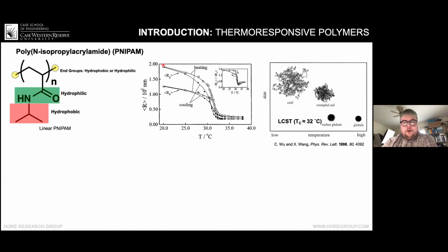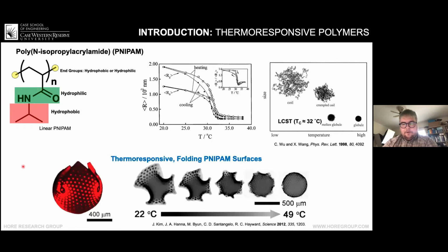So what's observed is that as you heat poly-NIPAM up above 30 degrees, the chains move from this coiled-like state, which is expected of a polymer in solution, to a globule state. So you can trigger this actuation of the polymer chain, and presumably the origin of that effect is that the strength of the interactions between this monomer here and the solvent are changing as temperature increases. So this has LCST behavior in water. And this is an example from a couple of years ago showing how this can be used to trigger folding of poly-NIPAM gels in response to heating by a laser.